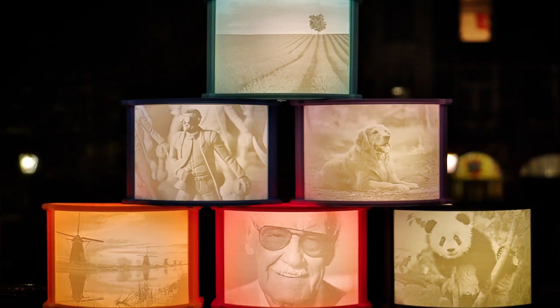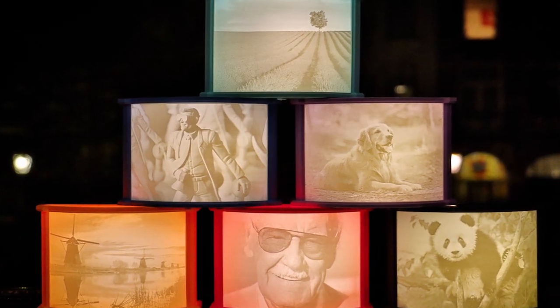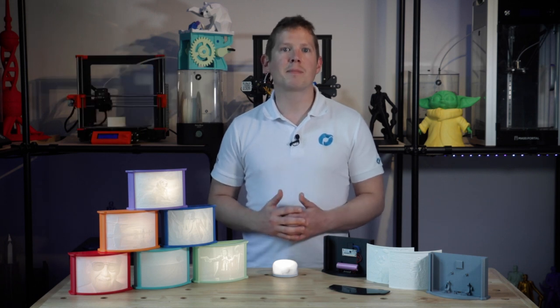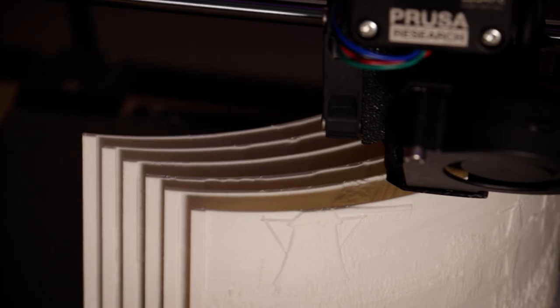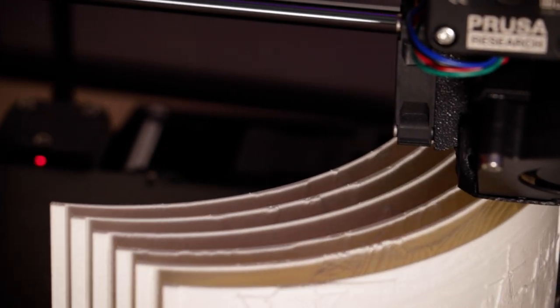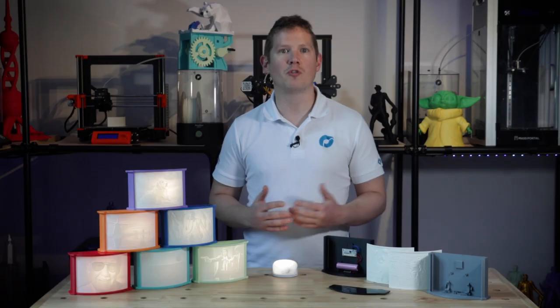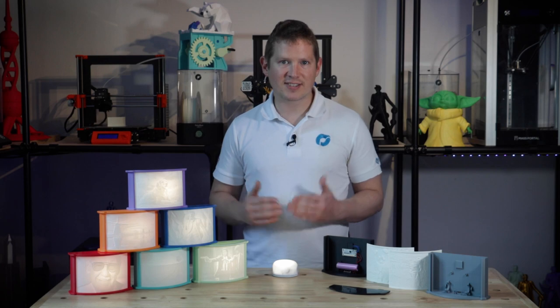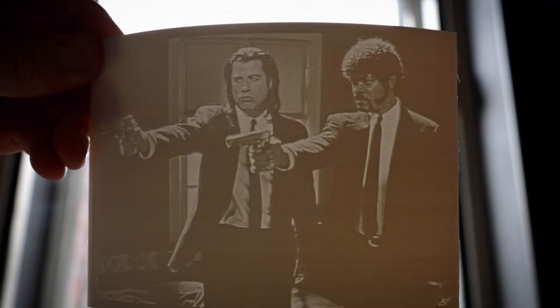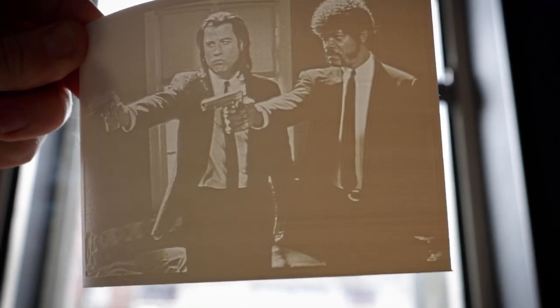Slicing your lithophanes will be the deciding factor on a clear, well-defined image. I will be using Simplify 3D, but all these settings can transfer across to your favorite slicer. When slicing lithophanes, I would err on the side of under-extrusion, as any over-extrusion is likely to leave little blobs or deform the image. As the grayscale between the thicknesses of the minimum and the maximum is very important, I think that a little less plastic is better than a little more.